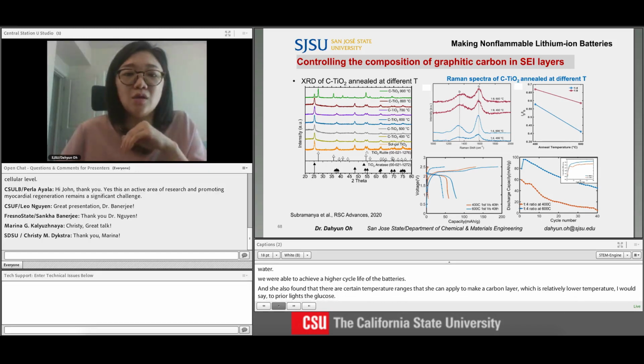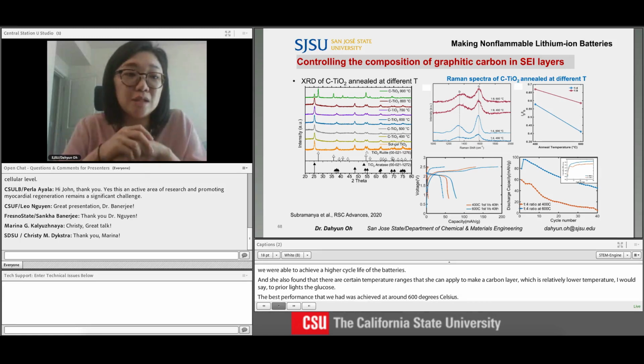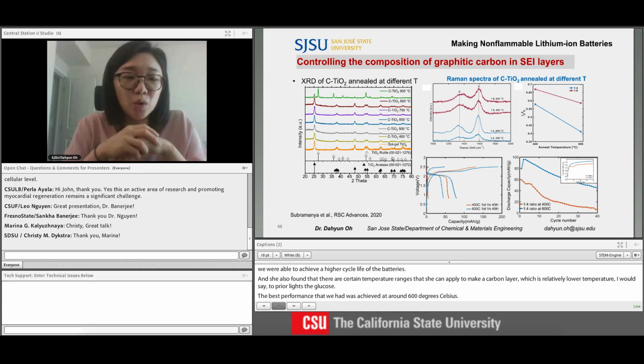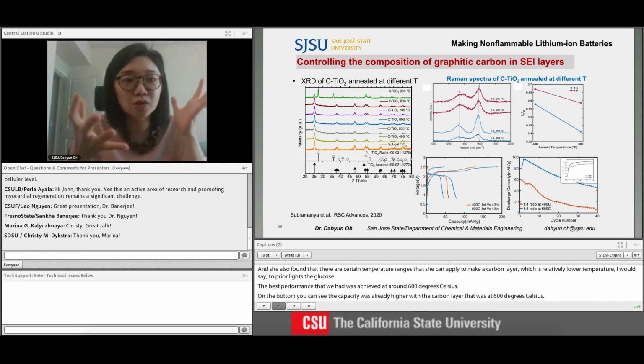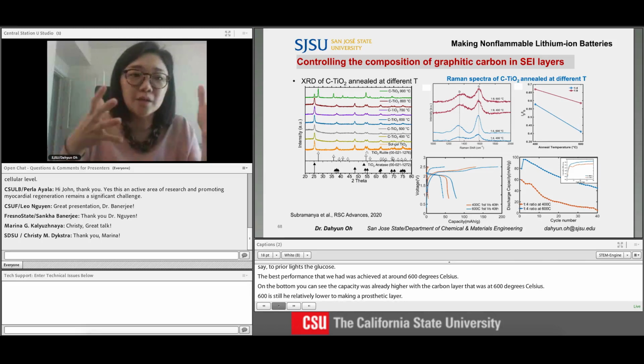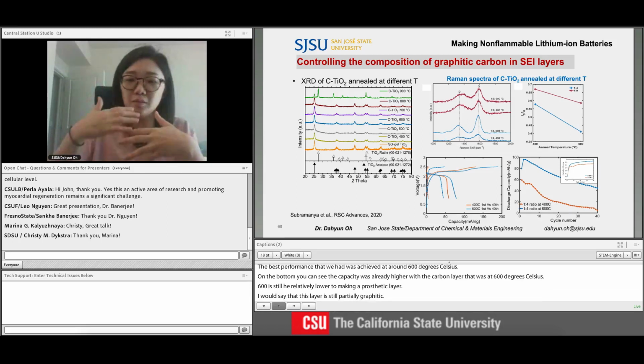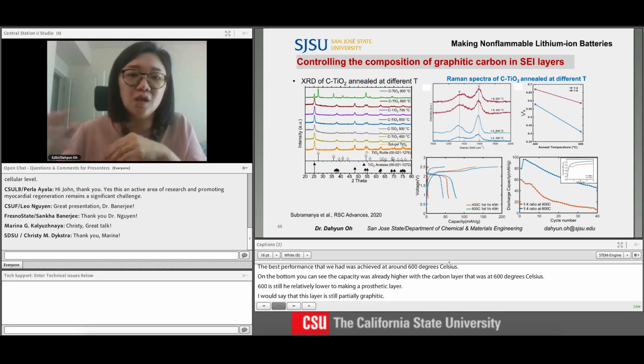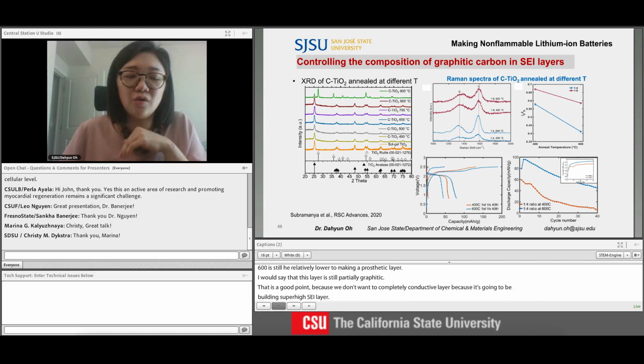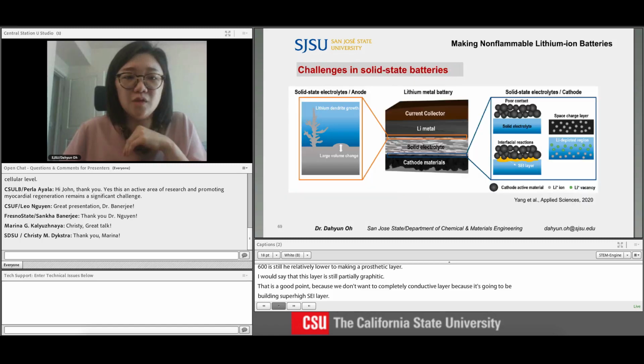On the bottom, you can see the capacity was way higher with the carbon layer annealed at 600 degrees Celsius. But 600 is still relatively low for completely making a graphitic layer, so I would say this layer is still partially graphitic. That's a good point, because we don't want a completely conductive layer, since it would contribute to building a very thick SEI layer. It should not conduct that much, but ideally still block the access of the water molecules. So that was the first project that we are focusing on.